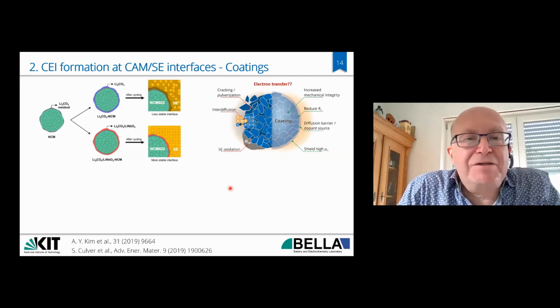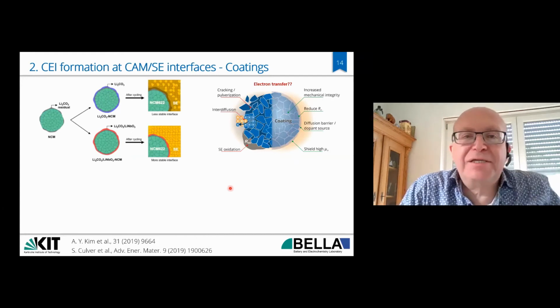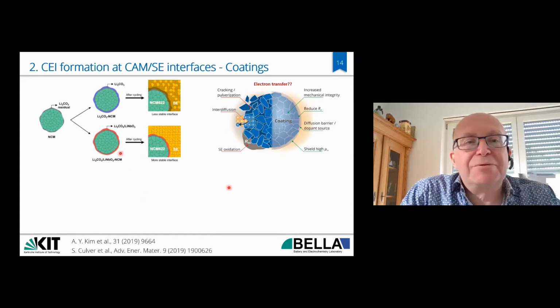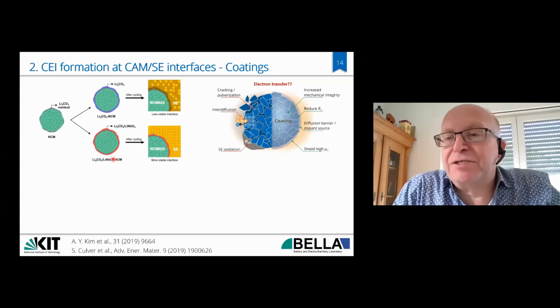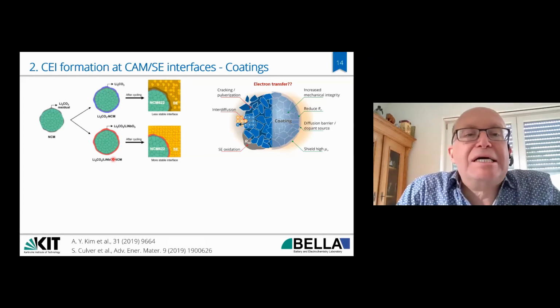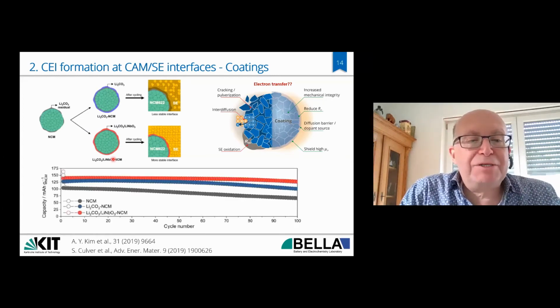And there are various concepts. I think the classic is lithium niobate, and in the Bella lab in Karlsruhe, we tried a modified lithium niobate coating. So it's essentially a mixed lithium carbonate, lithium niobate coating. We use the lithium carbonate, which is always present after storage on the high nickel materials. And by doing that, we see that the pure pristine material fades in the solid state battery much stronger than the coated cathode materials, where in fact the best results were obtained.